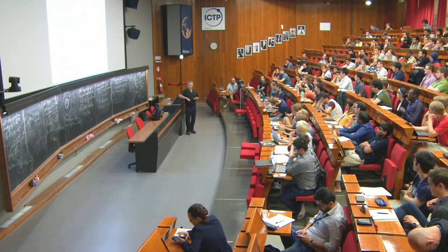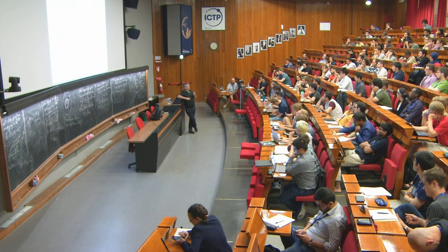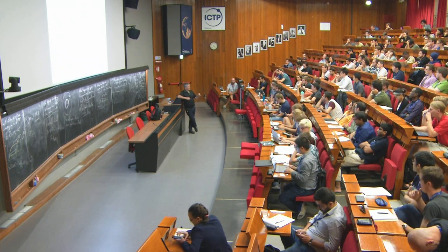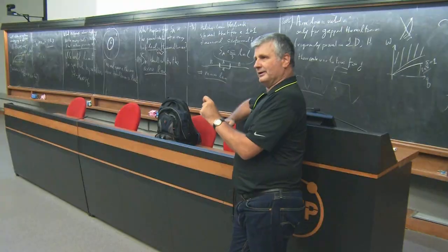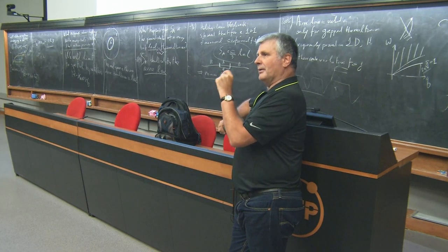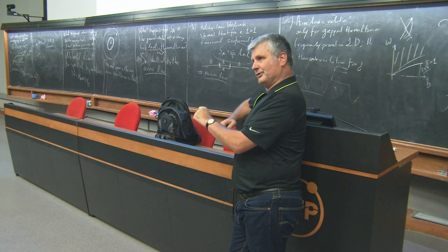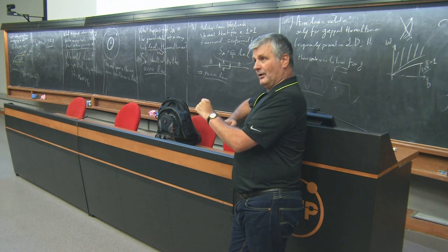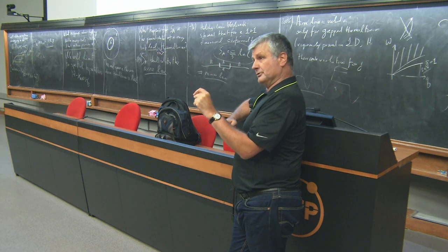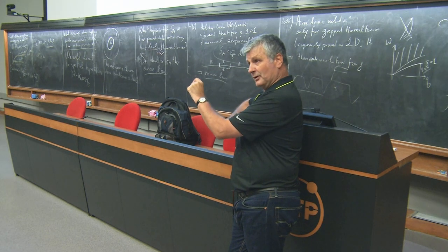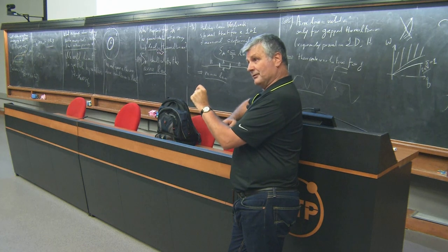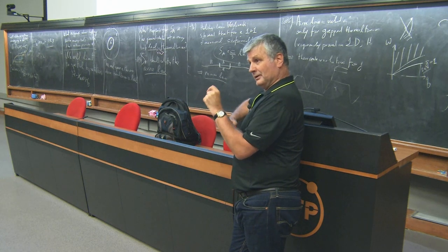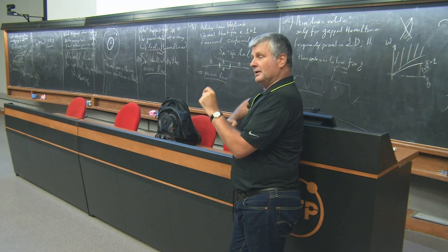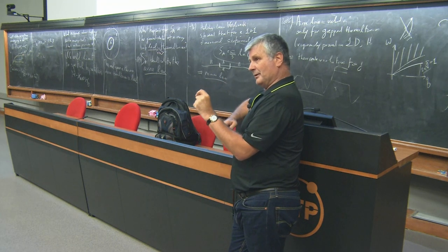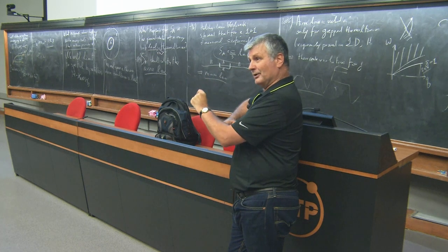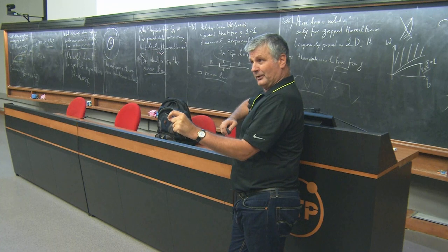Okay, good. So you define hydrodynamic transport as you do an experiment, you get a data set, you find features in that data set that you can model by taking into account the viscosity of the electron fluid instead of the resistivity. See, the resistivity that we're all used to is the property of the medium that the fluid is flowing through. The viscosity is a property of the fluid. And they have fundamentally different signatures in principle in experiments. So what you're always looking for is an experimental signal, ideally, that you can model with a viscous theory that you cannot model with a conventional one.